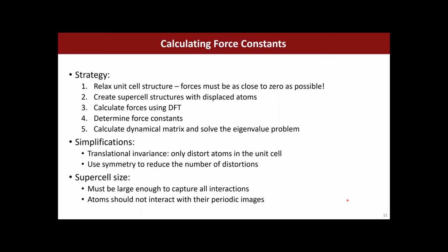And the other thing that we can do is we can use symmetry, which Dr. Hicks has talked about extensively in prior sessions, to reduce the number of distortions. If you displace an atom, for example, in the X direction, and it looks the same as if you displace it in the Y direction, for example, because your system is cubic, it will be a waste of computational resources to just calculate everything.